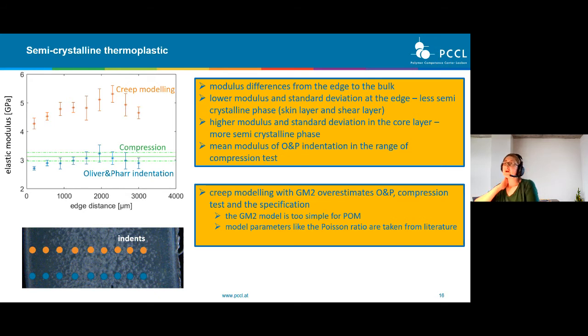And for the modeling, we also used parameters like, for instance, the Poisson ratios that are taken from literature. And therefore, the modeling overestimated compared to the Oliver and Pharr indentation.